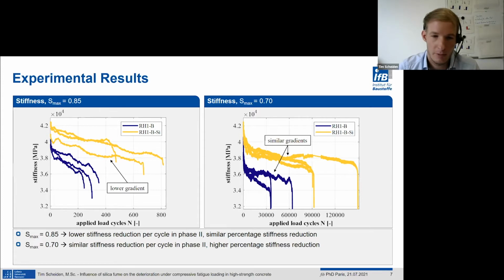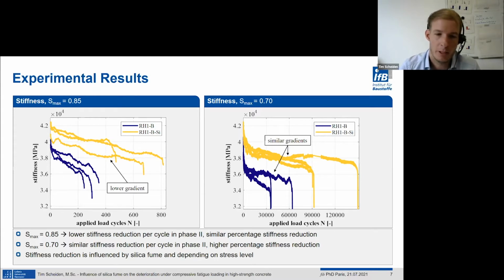At the lower stress level on the right side, the behavior is reversed. Here, the stiffness reduction per load cycle in phase 2 is similar, but due to the higher number of cycles to failure, the overall percentage stiffness reduction is higher. Here it can be stated that the addition of silica fume leads to a different stiffness development, depending on the occurring stress levels.